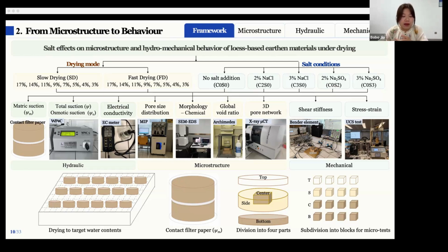And to investigate the macroscopic mechanical response, Bender element tests and unconfined compressive strength tests were conducted. The Bender element is also a non-destructive method that provides P wave and S wave velocities, and the S-wave velocity can be converted into the small strain shear modulus, which is relevant for evaluating the response to small vibrations, such as those induced by the train traffic in the railway region. And the UCS test provides the compressive strength and the stress-strain relationship, allowing us to assess the evolution of cohesion associated with the microstructure changes.